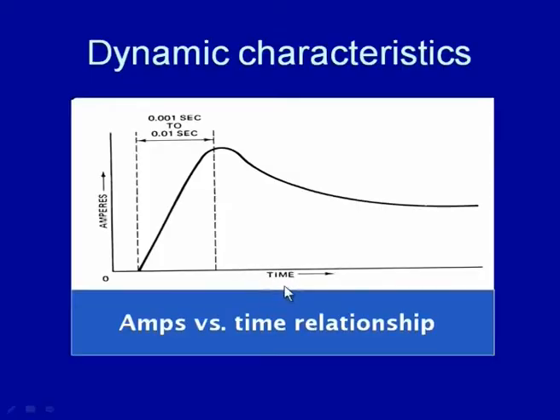If we see that on the x axis there is time, and on the y axis there is ampere, then you can see how rapidly the current has to increase from a very low value to a high value, within a short period of time ranging from 0.001 to 0.01 second. So, this fast response is required from the welding power source to deal with the changing conditions during welding.